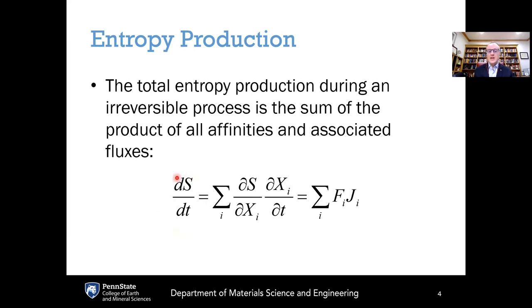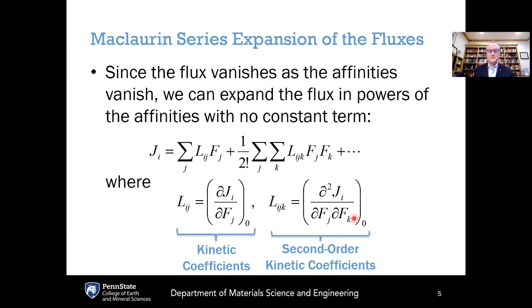So taking the time derivative of entropy, writing it in terms of the partial entropy with respect to a thermodynamic coordinate, times the time rate of change of that thermodynamic coordinate, that's the same thing as the product of the affinity, which is this first factor, and the flux, which is the second factor. So if you take the product of the affinities and the fluxes, add them up for all of the thermodynamic variables of interest, that gets you the rate of entropy production for the system.